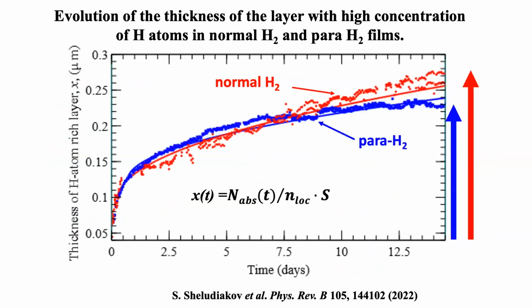At the same way, we calculated the penetration depth for this high concentrated layer in para-hydrogen, shown here by blue points. What you can see is that really, after 6 days or at the end, the penetration depth in para-hydrogen is slower than in normal hydrogen, which is counterintuitive - we thought that in para-hydrogen it should be faster.